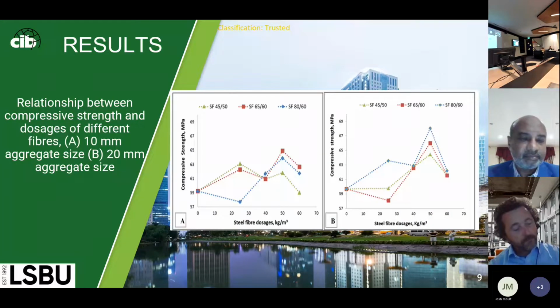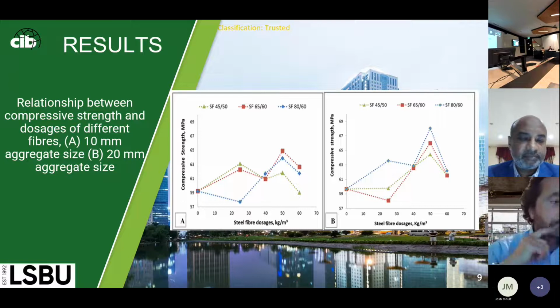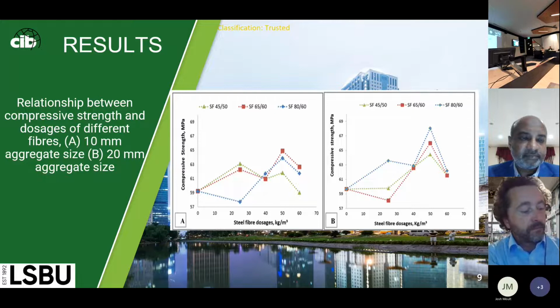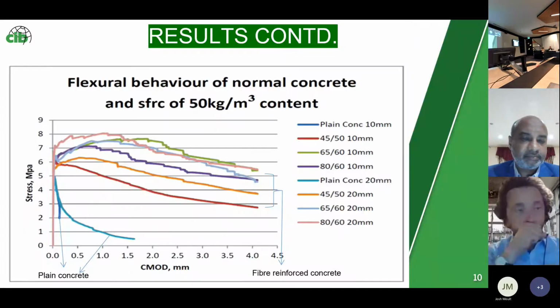And this is the compressive strength result. Steel fibers in concrete will slightly affect the compressive strength because it is mainly for the flexural properties. Even with the compressive strength, we could see that the optimum result is from the 50 kilogram per meter cube for both aggregate sizes. There was an increase until this level when it began to decline, because the more fibers in the concrete, the lesser the flow, as we saw in the workability, and that has a subsequent effect on the compressive strength.